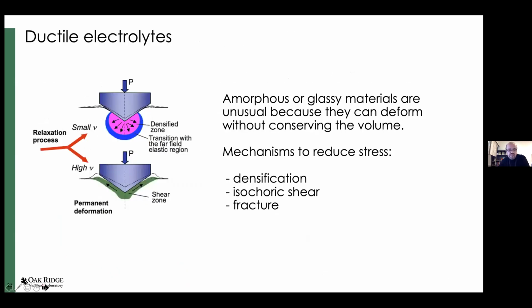And another way is to use ductile electrolytes and step away from the ionic crystals and look into the glassy electrolytes. So amorphous or glassy materials are very weird because in addition to just fracturing, they deform without conserving the volume. They can densify. They have just enough free volume to absorb plastic deformation by densification. So they have 3 mechanisms to reduce stress. Ceramics pretty much has only one, fracture. In case of glasses, you have 3 ways to reduce the stress buildup.